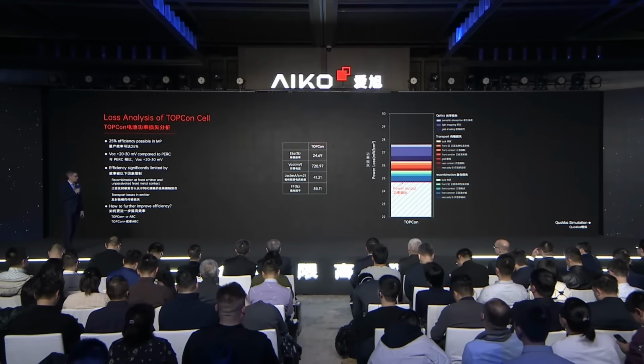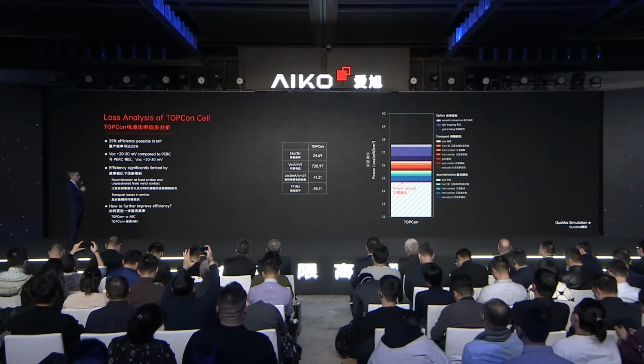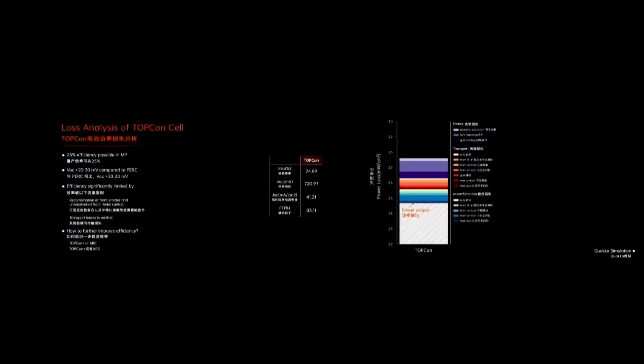And now I'd like to discuss with you the loss analysis of a TOPCon solar cell, as it is representative of a production line, has an efficiency of 24.7%. A high VOC of 720 millivolts, which is 20 millivolts higher than state-of-the-art PERC cells. The blue and green bars represent the recombination losses, and you can see that most losses still occur at the front side. Additionally, we have transport losses at the front side, and so the question is, how can we improve